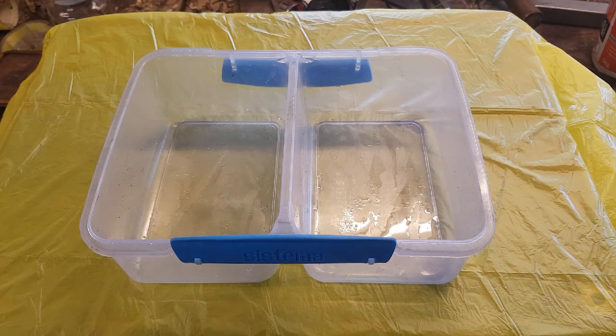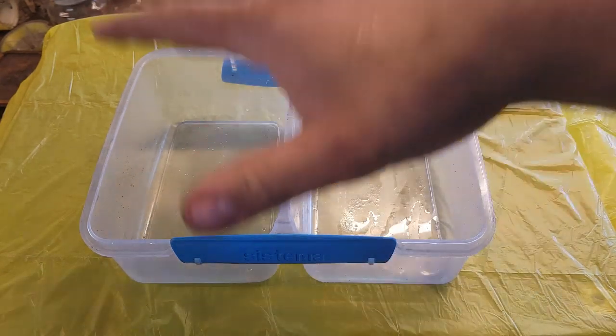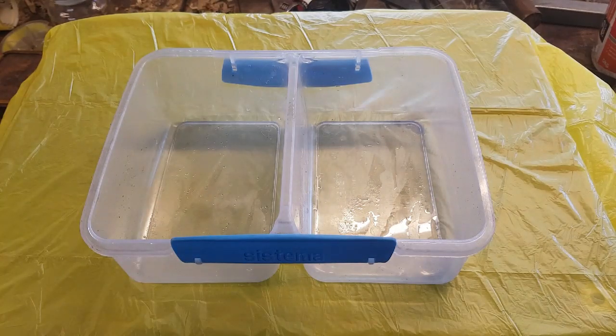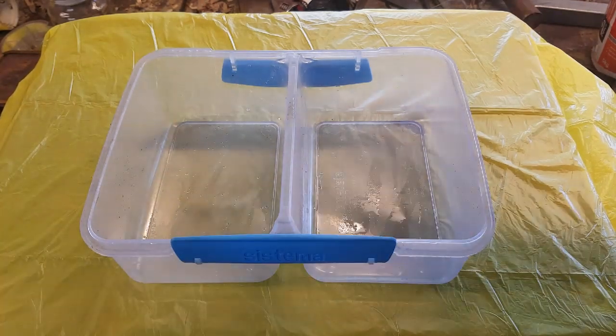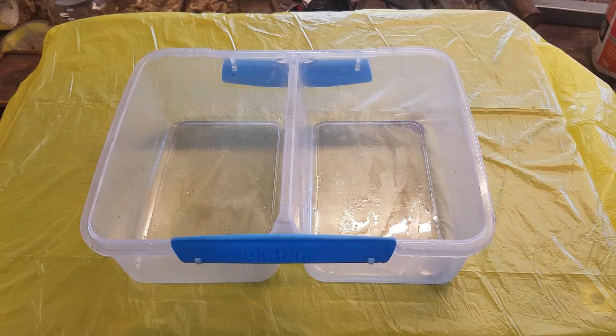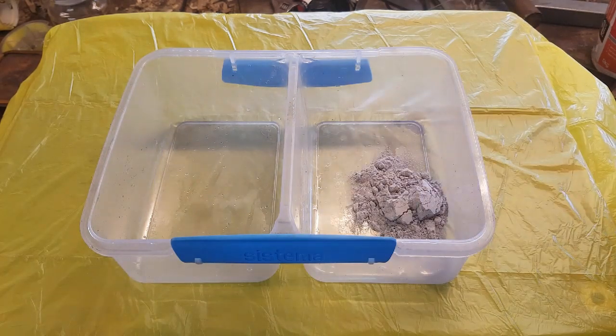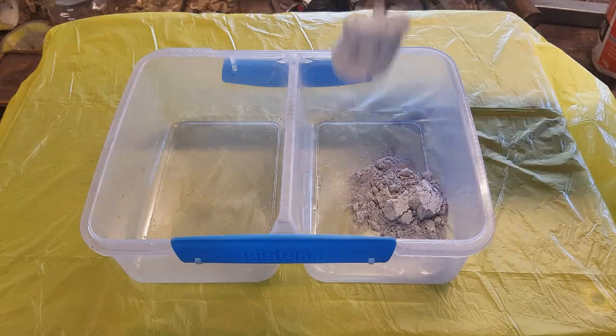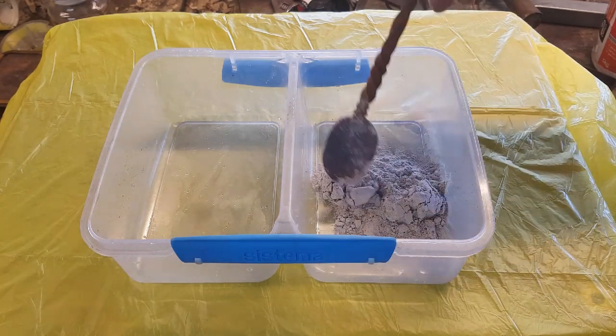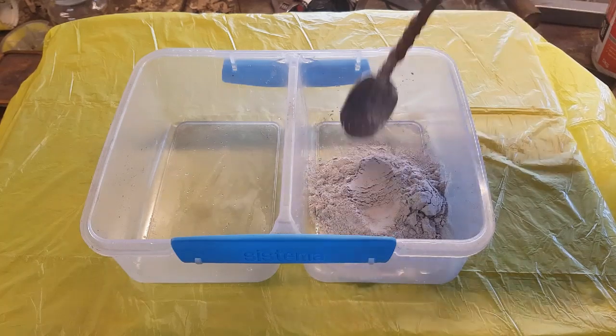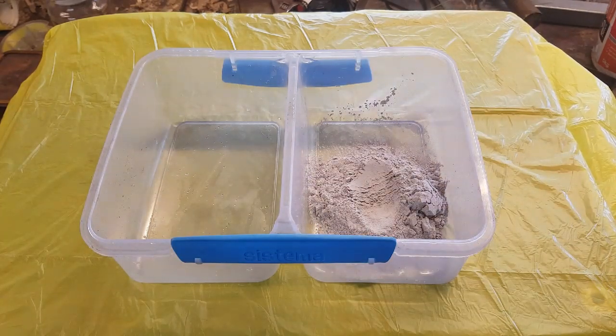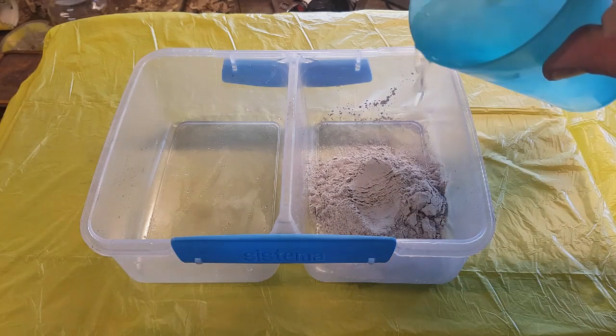The reason you want two pots is because you're going to mix two different consistencies of your clay. One is going to be a really runny consistency, what normal potters would call a slip, and the other one is going to be a much more dense version of the same clay. That's going to be for the actual Hamon. So what I'm going to do is add maybe 2 spoonfuls of the Satanite to this. I'm going to be making way too much Hamon clay, but I'm hoping I can seal this up and not lose too much moisture over time. You can buy Satanite pre-mixed.